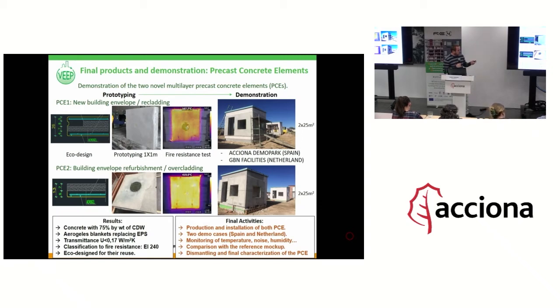We produced different prototypes of pieces of 1 square meter, and we performed different tests on the concrete and on the prototypes. We applied the fire resistance test to the elements. The result was that we are producing precast elements with concrete with more than 75% by weight of recycled material, with an insulation layer made with circular aerogel, and we arrived at a transmittance value lower than 0.17 watt per square meter Kelvin. And the fire resistance classification is more than 4 hours.